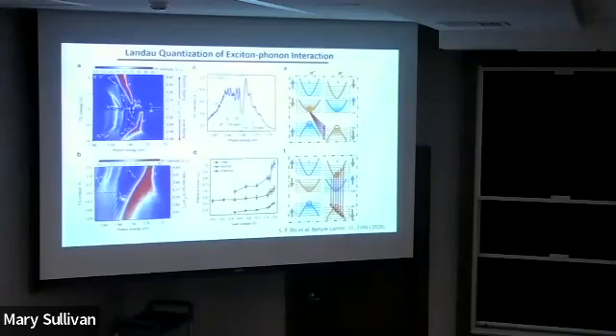But I said this is a phonon replica, right? If you have a phonon process going on, you don't have the same selection rule anymore. Actually, this selection rule constraint is greatly lifted. As a result, this electron here can recombine with any of the holes here. So you're going to see the energy spacing of this light emission roughly at the Landau level spacing in the valence band. For this one, you're going to see the summation of the valence band and the conduction band. So that's why it's roughly 1 to 2.